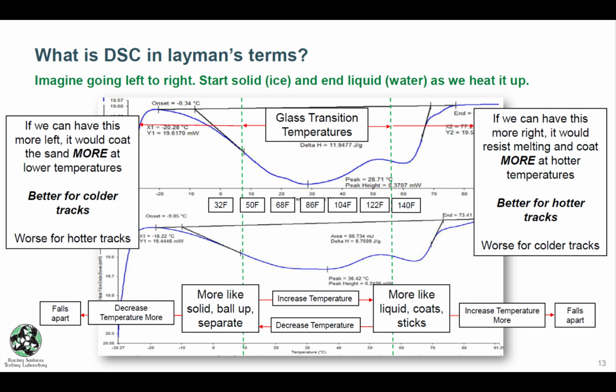So what am I really talking about here? If we're taking a look at the thermal properties for both Windstar and the old Turfway Park track, if we could change the temperature at which it starts acting like a solid versus a paste, or if we could move the melting points of these waxes, we can tailor these materials for working in colder conditions like Turfway, or potentially Woodbine towards the end of the meet, or maybe we can move it to the right so it's better for tracks like Santa Anita, where the temperatures are going to be a lot higher. As we increase temperature, we know that the wax tends to act more like a liquid. It coats, it gets a little sticky. But if we decrease it, it starts to become more solid. It'll start balling up.